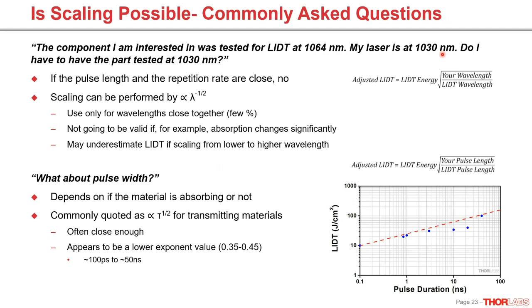But you couldn't, for example, scale a part tested at 1064 down to say 266, because the properties are going to change significantly. And this particular scaling may underestimate the damage threshold if you're scaling from a lower to a higher wavelength, which means you may not be able to use your laser, which isn't quite as catastrophic as some of the other scaling issues, but just something to bear in mind. Obviously, if you overestimate the damage threshold, that's much worse than if you underestimate.